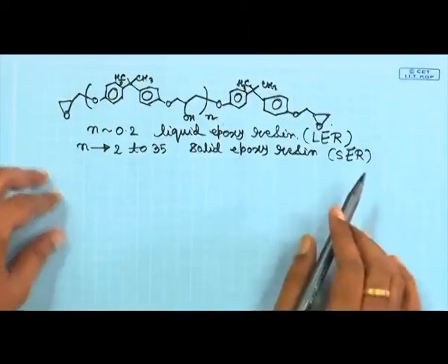You can also calculate according to the molecular weight, because if you take the weight equal to the molecular weight, you will get 2 equivalents of epoxy units. So, that divided by 2 will give you your epoxy equivalent weight, and that is also important because you want to ultimately cure this material. You can react with a cross linker in order to make a thermoset material. So, you want to know how much epoxy linkage is there, so that you will use that much amount of cross linker. All right.